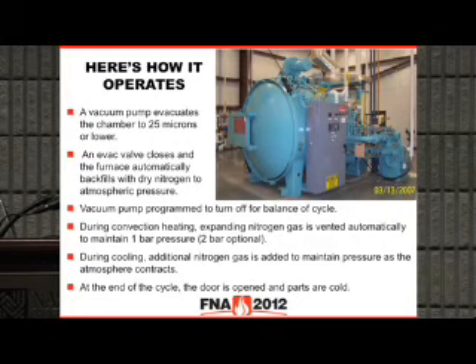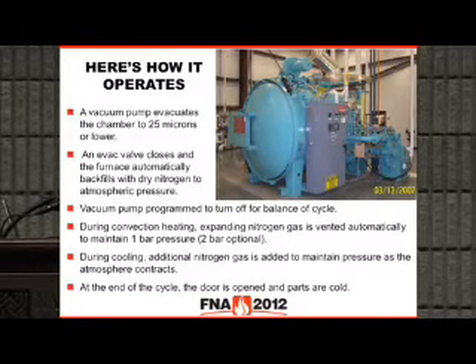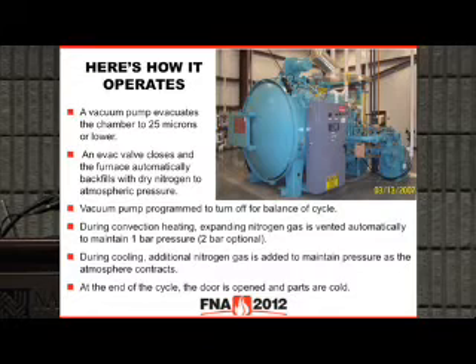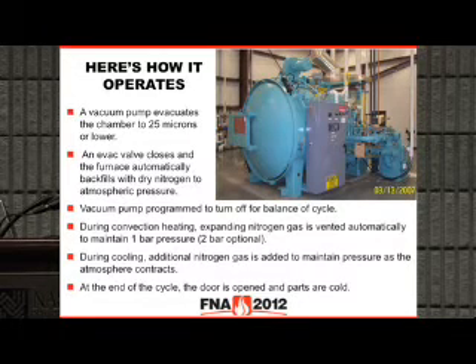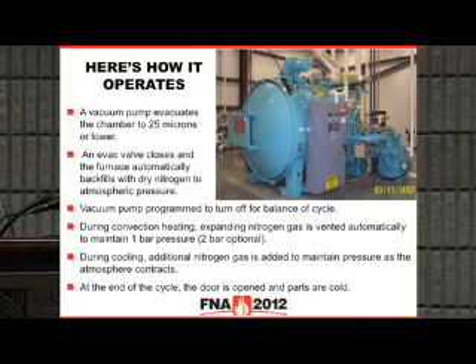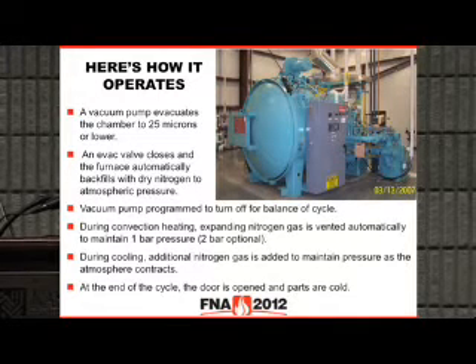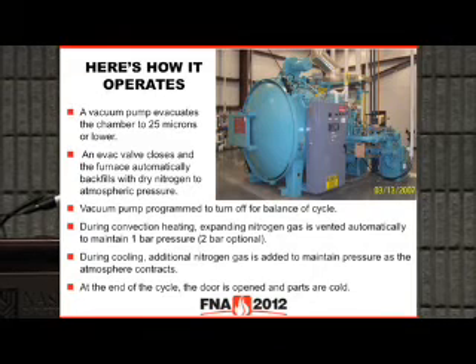Once the system has pumped the furnace down to this level, 20 minutes depending on the size or the vacuum level you're going to, we backfill to atmospheric pressure with dry nitrogen, one charge. A 36 by 48 by 36 furnace would use roughly 320 cubic feet. Then the heating system turns on, and we're actually heating under convection. Most people will run at 1 bar convection. We have equipment that can run at 1 or 2, so you get a faster heating rate at 2 bar. You also get a faster cooling rate at 2 bar.